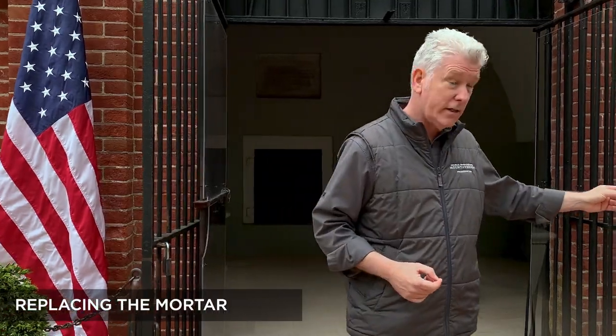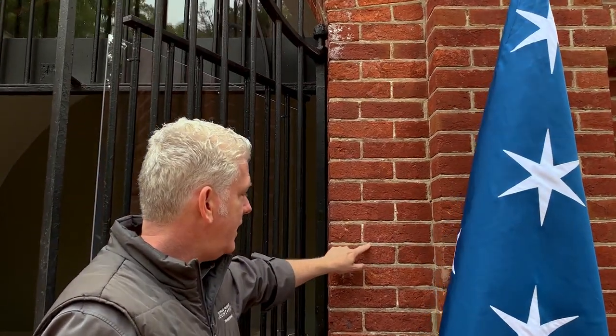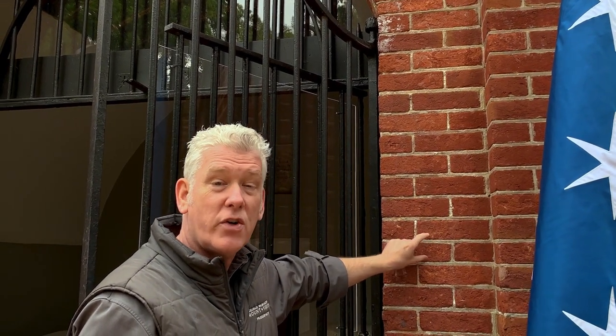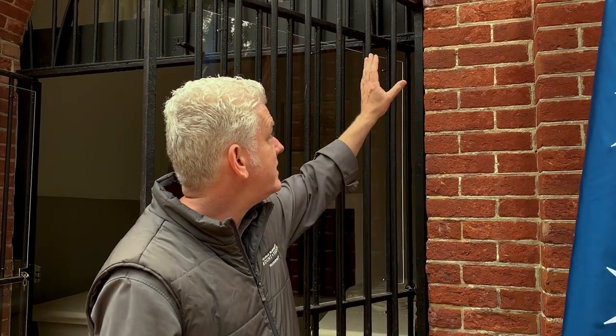If we take a look over here, you can see above me there looks like a little bit of white smudging on the surface of the brick. That's caused by natural salts in the brick that get drawn out by water standing in the brick. And when that water starts to stand in the brick, when the mortar that holds the brick wall together is too hard or is harder than the brick. When this building was originally built, a softer lime-based mortar was used to construct it. In the 1930s, during one of those in-depth repair campaigns, the only mortar available was a harder cement-based mortar. And now, almost a hundred years on from that 1930s intervention, we're starting to see the salt beginning to effloresce, or migrate to the surface of the brick. That causes the surface of the brick to begin to deteriorate.